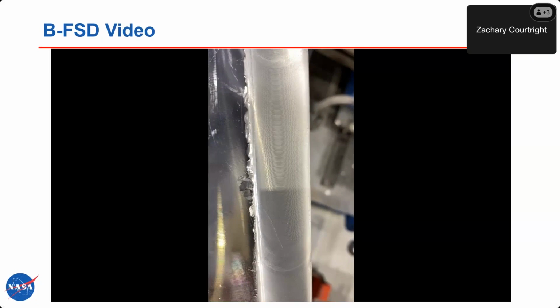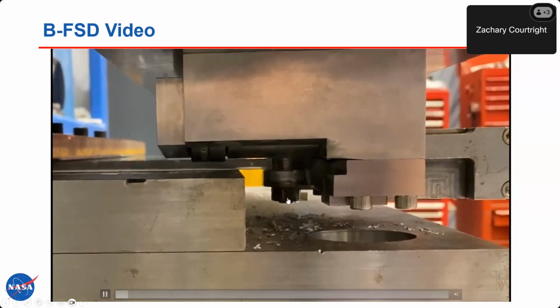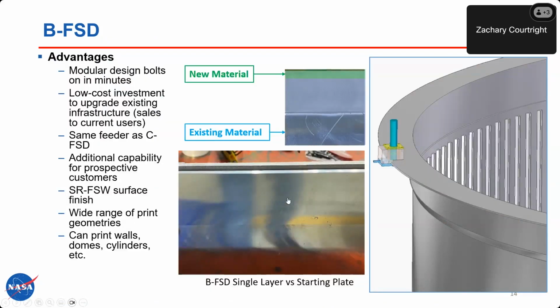But in general, getting that flash down to a very low level is common to development for friction stir processes, where you optimize the parameters to get the flash to the lowest level possible. So that's not something that would require any amount of post machining. It's pretty easy to get off. But that's Bobbin Friction Stir Deposition. Okay, so there's another slide.